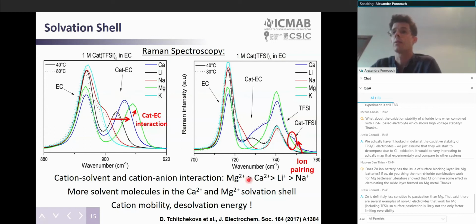This will, of course, have a strong implication for the desolvation energy of the cation when we want to go for plating and stripping, or insertion/deinsertion for the cathode material. We also confirmed that we have more solvent molecules in the calcium or magnesium solvation shell when compared to lithium and sodium.